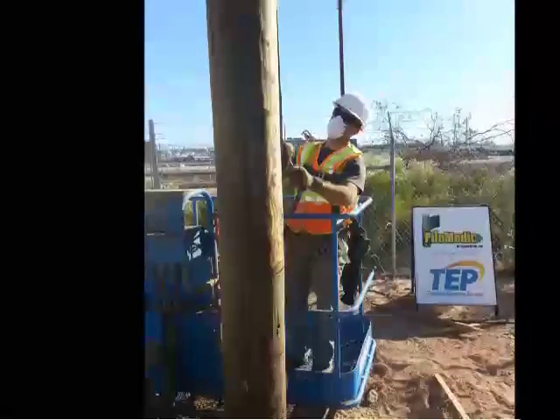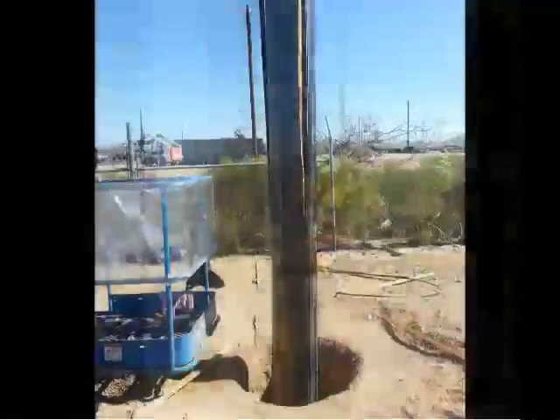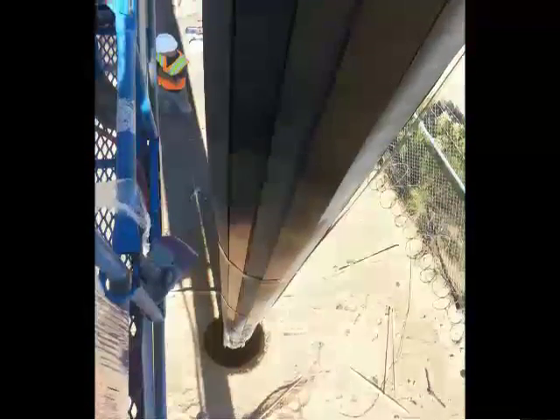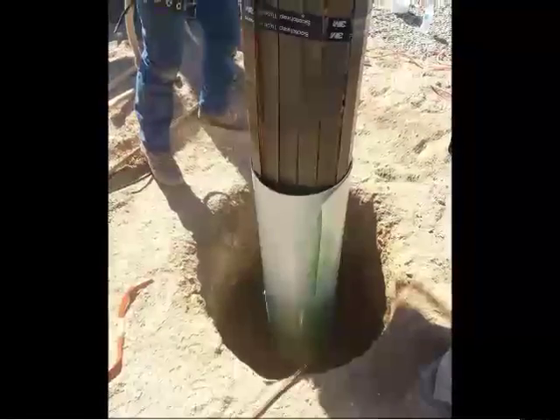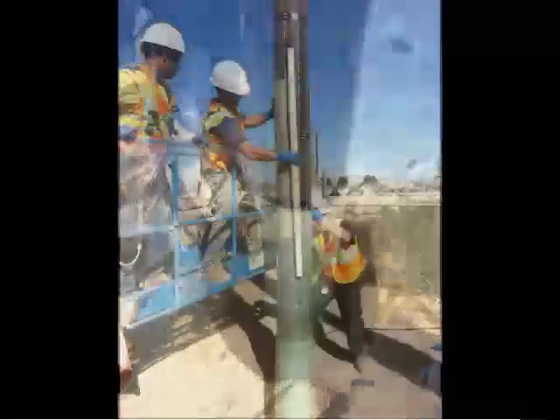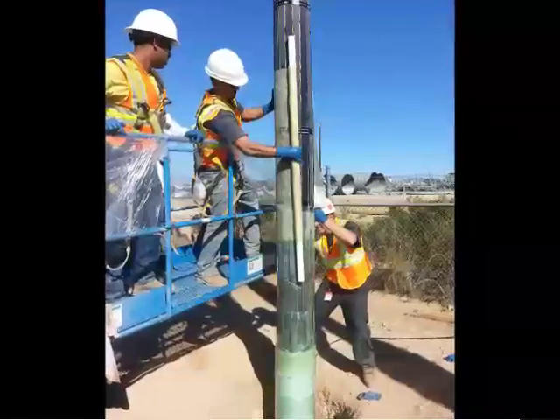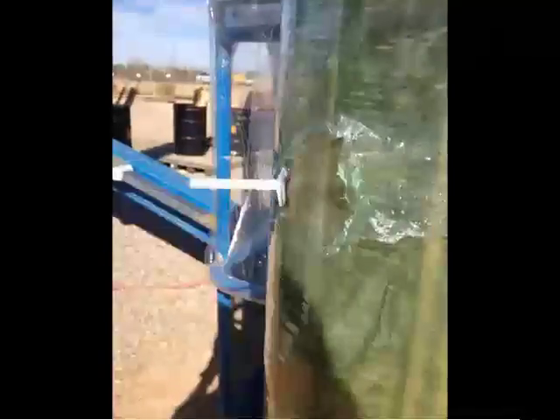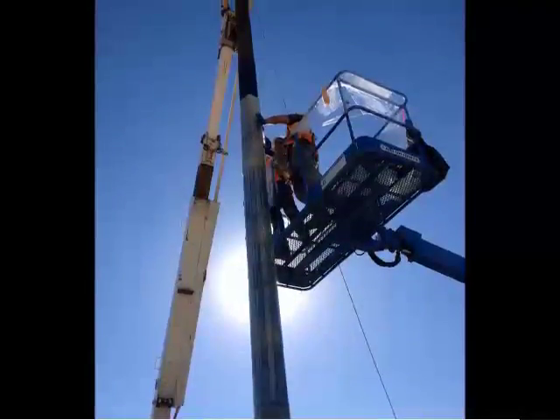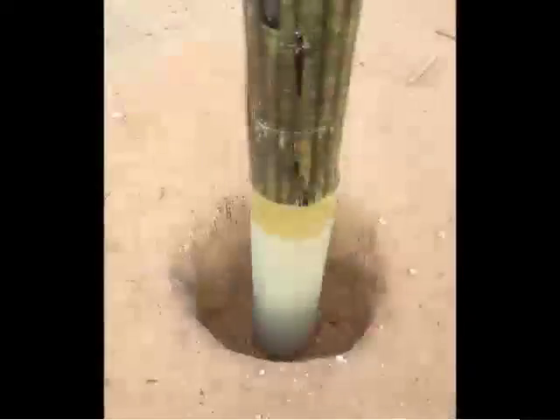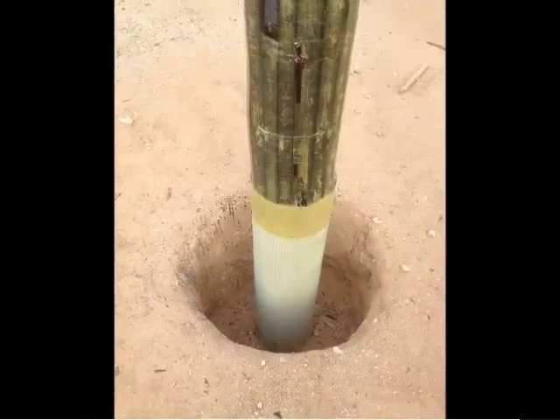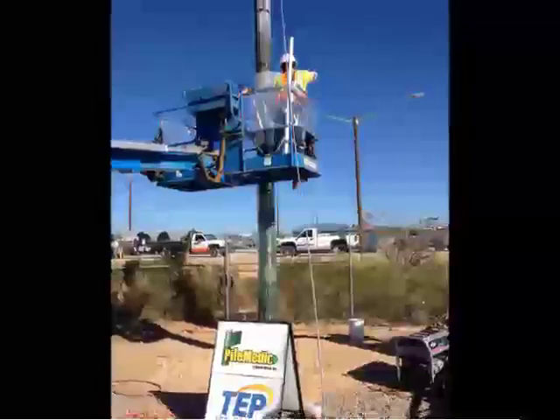The strengthening of the pole consisted of the following steps. 1. Provide longitudinal carbon strips along the height of the pole. 2. Wrap the pole with PileMedic laminates or QuakeWrap FRP fabric. 3. Inject our low-viscosity resin to fill all the voids and cracks in the pole. 4. The repair covered the elevations from 4 feet below ground to 20 feet above ground. This procedure allows the pole to remain in service during the repair.